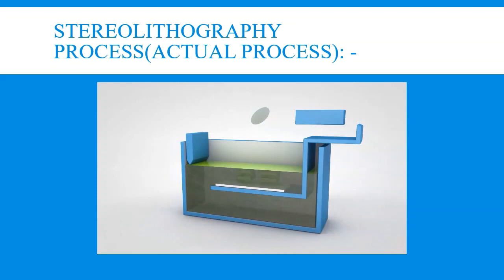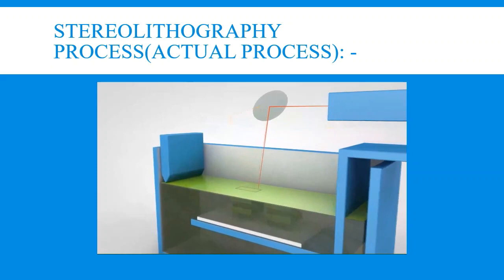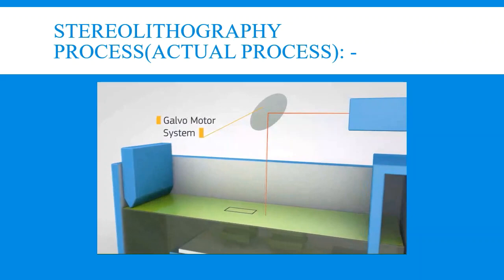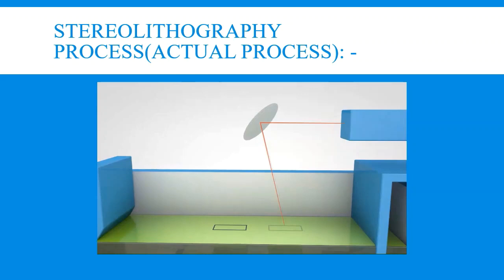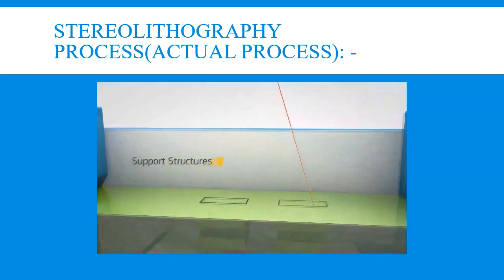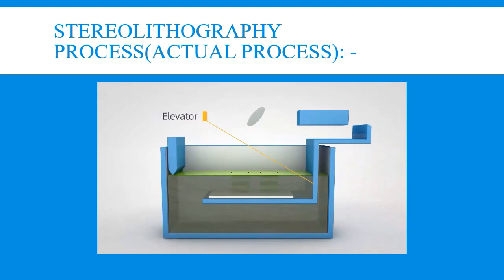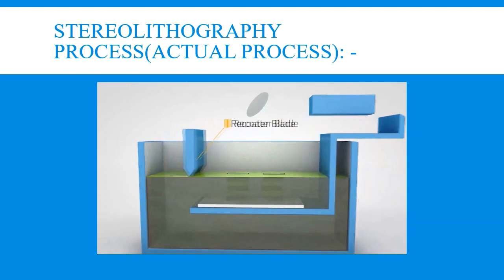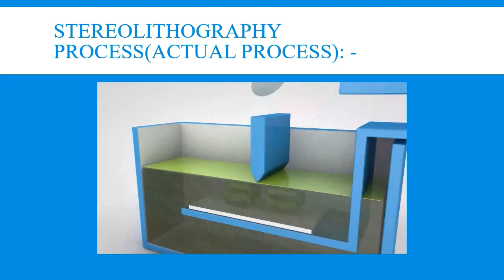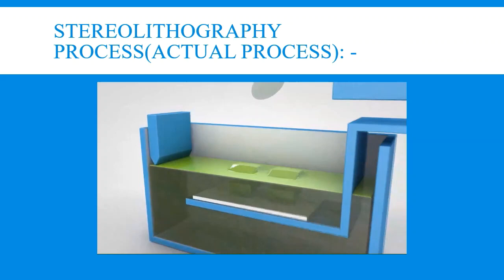In the initial step of the stereolithography process, a thin layer of photopolymer resin is exposed above the platform, where the laser hits the platform painting the pattern of the object being printed. The resin hardens instantly when it comes in contact with the UV laser, forming the first layer. The computer directs the laser according to the geometry of the CAD file, printing both the support structures and the part geometry. Once the initial layer has hardened, the platform is lowered and the re-coater blade moves across the platform to apply the next layer of resin. The laser again traces the next cross-section, which instantly bonds to the previous layer. This process is repeated until the entire object is formed.